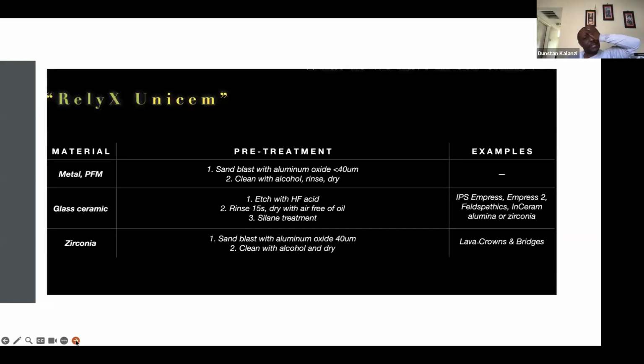So as we conclude, many of us are not going to have different cements in our practices. So you can use nowadays a self-adhesive resin luting cement, like RelyX Unicem. And this material can be used for all your cementing needs. However, the surface has to be treated differently before you can use this.